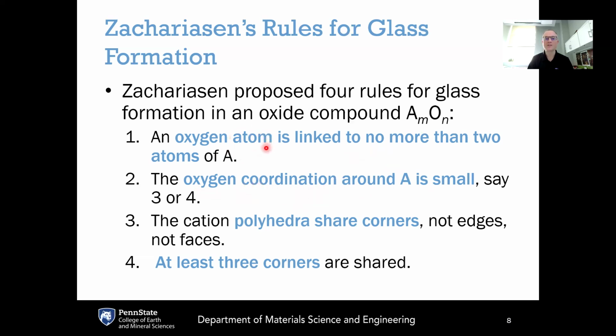The first rule tells us how many A atoms are linked to each oxygen. So there's no more than 2 of the cations linked to each oxygen, so the oxygen can provide a bridge between those 2 different cations. The second rule defines how many oxygens are around the cation. And what Zachariasen is saying is that it should be a small number, specifically 3 or 4. So we've got 3 or 4 oxygens around each cation, and then 2 cations around each oxygen. Together, these first 2 rules define the short-range order for the glassy state. Why is it 3 or 4?